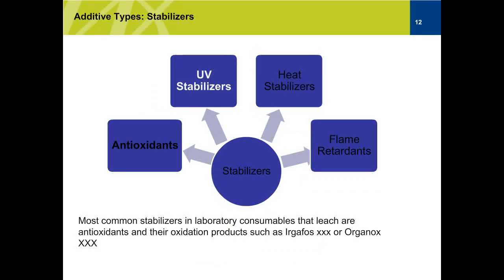So let's talk a little bit deeper about stabilizers, because these are the ones that we see most in our leachate profiles. Basically, most plastics, or most labwares, will have antioxidants, and antioxidants are going to be placed sometimes in the manufacture of the resin and also during the manufacturing processes. These antioxidants are a type of stabilizer that protect the material during the processing and extend the material's longevity. And they're used to prevent degradation of the polymer that can result in loss of strength, flexibility, and color.